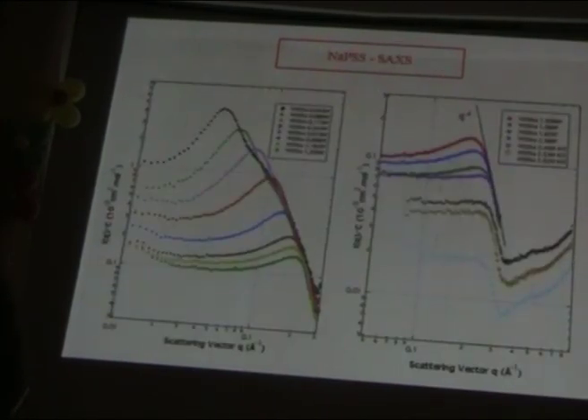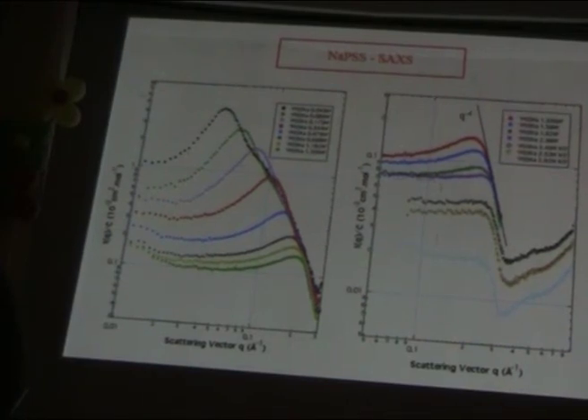So, we have used different polyelectrolytes with different intrinsic stiffness here. For example, for the sulfonated polystyrene, you have 10 angstrom for the naked persistence length. If you go to the PDADMAC and other polyelectrolytes, polycations, you have 30 angstrom. And if you go further with the hyaluronate, for example, you have something which is twice the PDADMAC. So, I give you some small angle X-ray scattering results here.